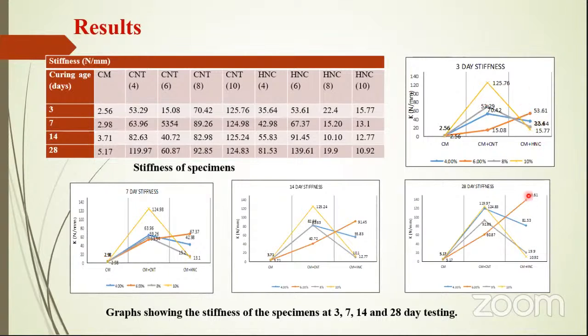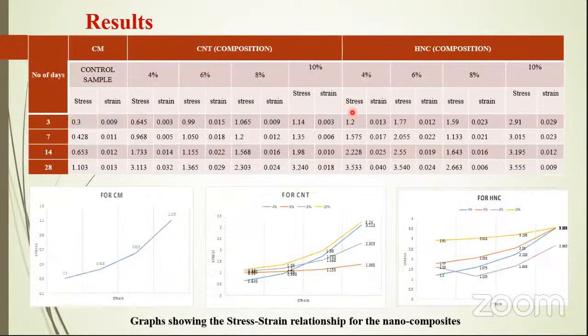Similarly, the stiffness also, as you can see, as the loads increase, HNC has lower stiffness and CNT has higher stiffness. Maybe this is the reason the strength gain is slow, because the stiffness is more. But slowly the stiffness here reduces and then the strength increases, whereas in case of HNC, the stiffness is initially smaller and then it increases, the vice versa of the CNT. So the strength gain is faster and higher in case of HNC rather than CNT.